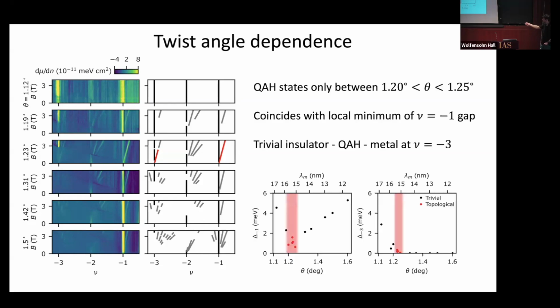We can do a little bit better. We have additional data that I'm not showing you here, just not to overwhelm you in the slide, but we can quantitatively extract two things. One is the size of the energy gap at nu equals negative 1 at zero magnetic field as a function of twist angle, or equivalently Moiré wavelength, and also the topology. So these red dots are the topological states. They exist in a very narrow window of about 1.2 to 1.25 degrees. To lower twist angle, to higher twist angle, the gaps become bigger actually, but are topologically trivial. And so we think there are actually two different topological transitions that are occurring here as a function of twist angle to possibly different trivial electronic states at nu equals negative 1.